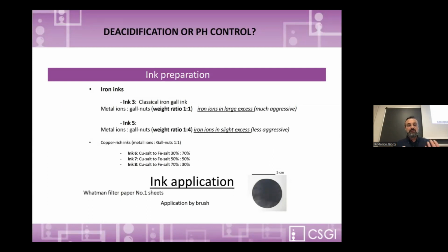When we use gall and nuts in the weight ratio 1:1, that is the ratio that we usually find in the old recipes, in this condition, looking at the number of moles involved in the process, we have a very large excess of iron. And this means that we have an ink that is much more aggressive. If we modify this weight ratio, we can get iron gall inks which are less aggressive.